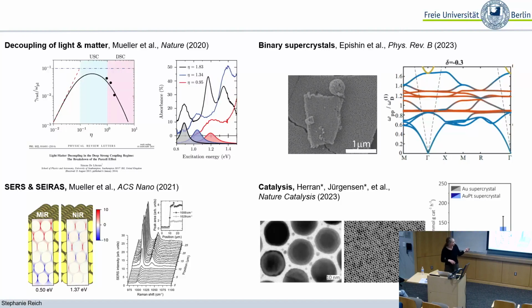We also started to look at binary supercrystals. And if you look closely here, you can see that this is a cubic structure and is actually the cesium chloride structure that we grew by using gold nanoparticles of different size. Instead of just having one that will always give you FCC, we started to use 2 types of nanoparticles and also developed the theory for that.